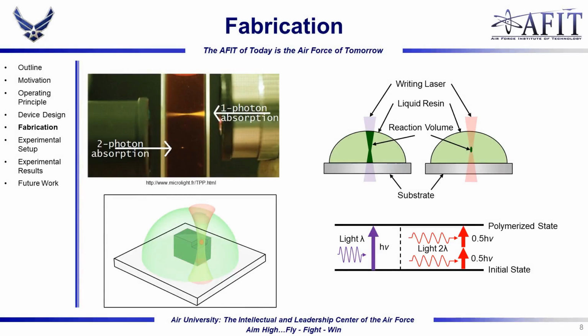Now, we fabricated our device using two-photon polymerization. This is an additive manufacturing technique, similar to stereolithography 3D printing, in which a photoactive resin is selectively polymerized or solidified with a high-energy laser. Traditionally, this is done with UV light, but the same polymerization energy can be achieved with 2 photons at a higher wavelength. The volume within a laser beam that has sufficient energy for 2-photon polymerization is significantly smaller than the volume capable of single-photon polymerization. Thus, a much smaller voxel, or 3D pixel, can be used to build structures within the resin when using 2-photon polymerization.